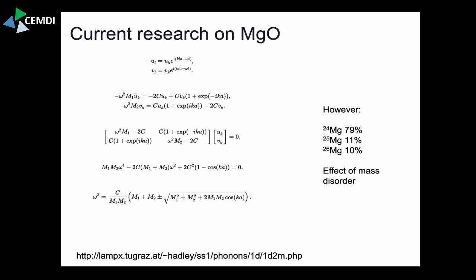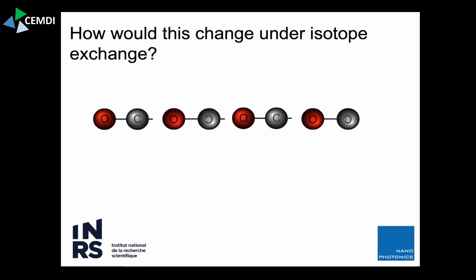But silicon is Raman active. Here the question is, would magnesium oxide, or should magnesium oxide be Raman active, because it has this composition of isotopes that eventually break this translational symmetry. If you change the masses by 2, 4, 8%, whatever it is there in detail, you would expect that the total polarizability of that chain is no longer exactly 0. And for that matter, the question is, well, is it sufficiently different from 0 to actually show up in the Raman signal or not?